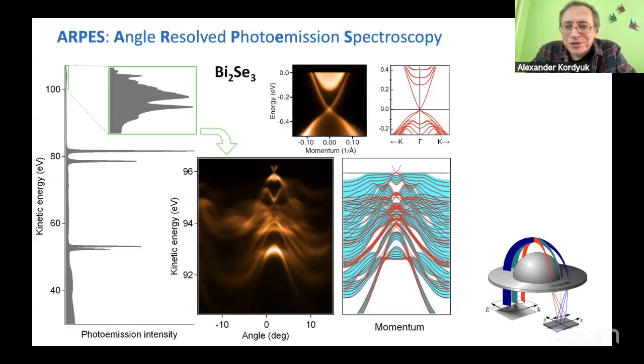And it is actually how you usually in an experiment could distinguish the surface state from the bulk state. If you have some two-dimensional bulk state or a surface state, you could just contaminate the surface a bit, just to put it, and they completely disappear.